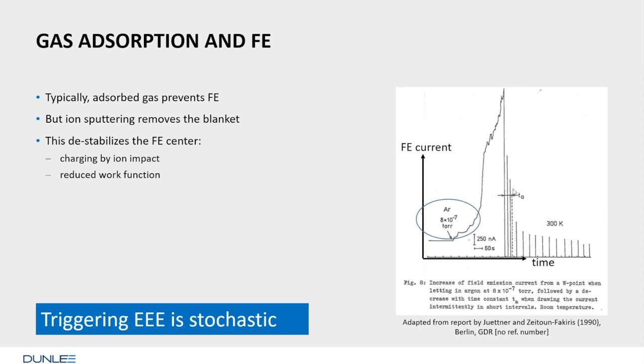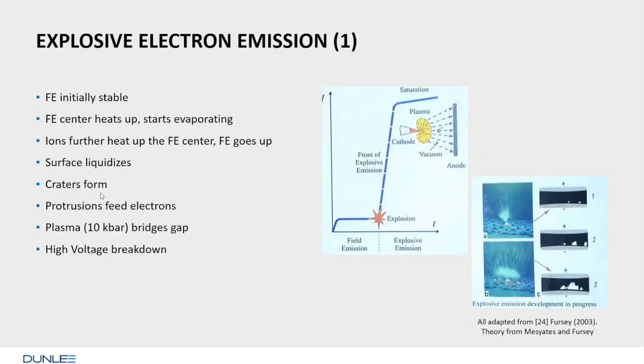And you see here that the field emission dropped down to the old level. And the time constant here was exactly the time needed for the residual gas, carbon monoxide, or what was it, to be reabsorbed. So ion sputtering removes the blanket, and this destabilizes the field emission center. This is, again, a stolen chart here from Mr. Fursey, his work. And Fursey, together with Mesyats, a Russian physicist, explained this EEE effect for the first time.